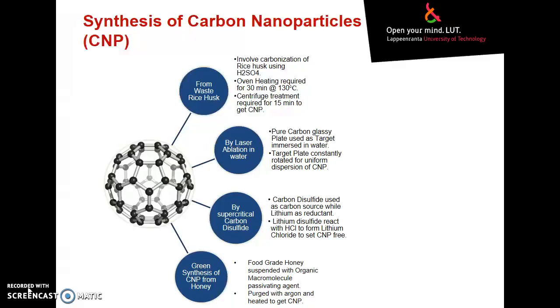The third one is the synthesis of carbon nanoparticles by using supercritical carbon disulfide. In this synthesis process, the carbon disulfide reacts with lithium, in which the lithium is converted into lithium sulfide. For further reaction, lithium reacts with hydrochloric acid to form lithium chloride, which is easily soluble in water, and we will get the carbon nanoparticles in very pure form.